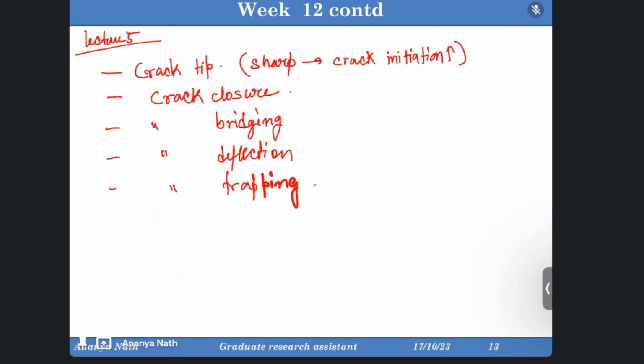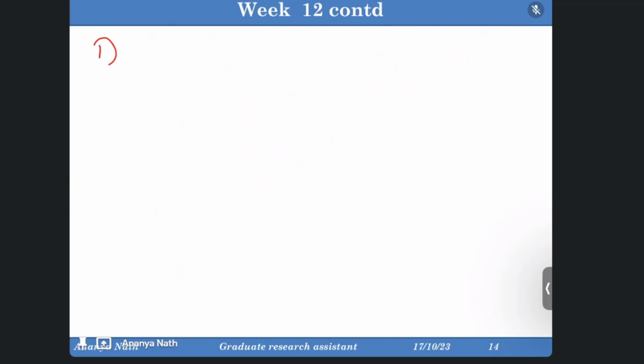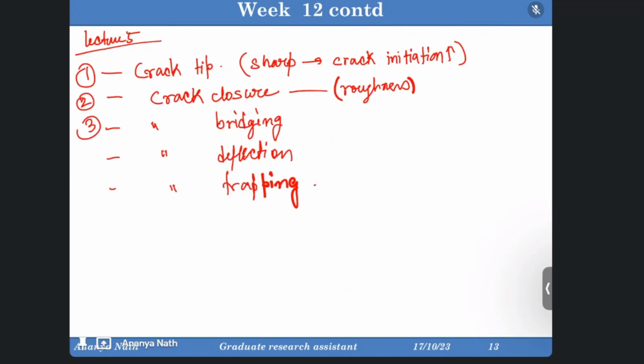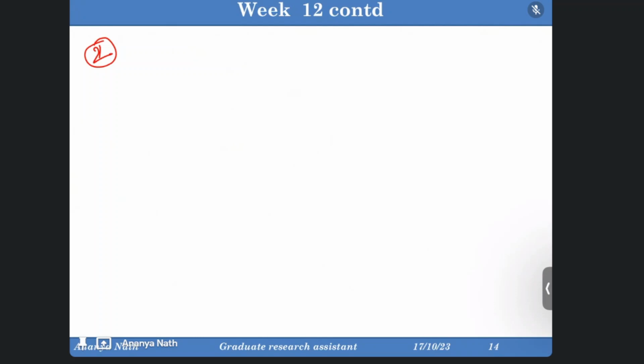So what can happen? One thing is crack closure. The most important feature for crack closure is that the crack closure happens due to the roughness present over the matrix crack face. So this is because of the roughness. If there is a crack, one is the tip, which I have already discussed. So I'm talking about the second one. If this is the crack which is present over there, this is the surface, and if there is some surface roughness, as the crack propagates, these 2 points will touch each other with time and with the propagation, and it will touch each other like this, and it will form a closure.